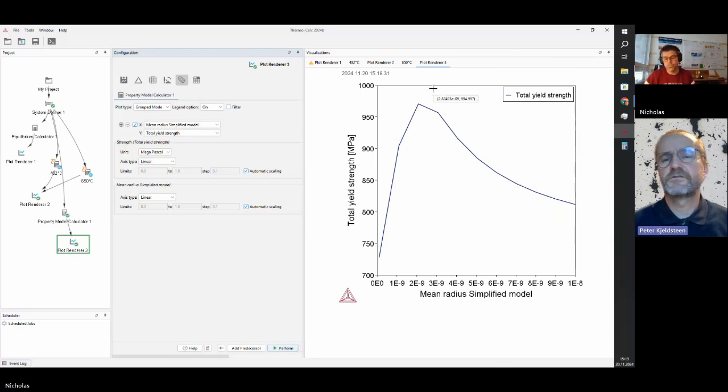Isn't it also agglomeration when they grow? Absolutely, they agglomerate into fewer particles. Yes, you're right. That's ripening, right? You just have a few big ones, and the dislocations have a lot of space on either side just to pass through them. Exactly. So that's the mechanism.